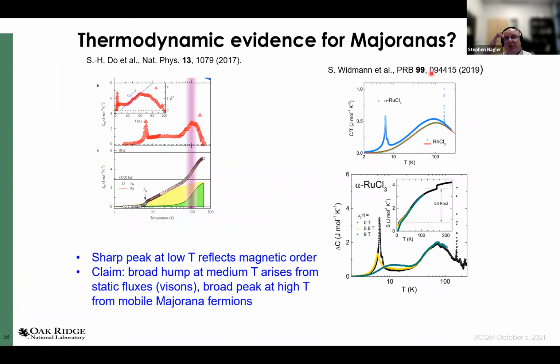There's one other thing before I start talking about neutron scattering that's interesting to note. You may remember that I mentioned that for a pure Kitaev model, the specific heat has 2 peaks as a function of temperature: the highest temperature corresponding to the mobile Majorana fermions, and the low temperature peak to the visons. Here are some measurements of a zero field crystal that did show this broad peak you might expect from the mobile Majorana fermions, up at 100 Kelvin, about 15 times the transition temperature. That was done by the Korean group.